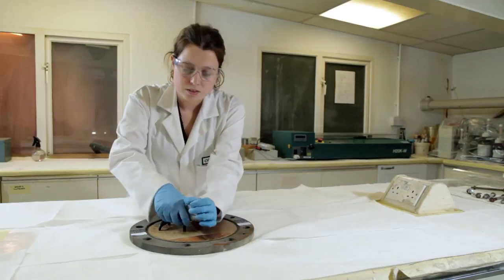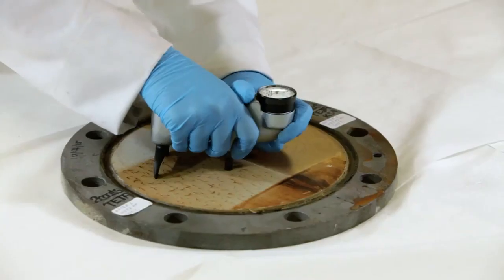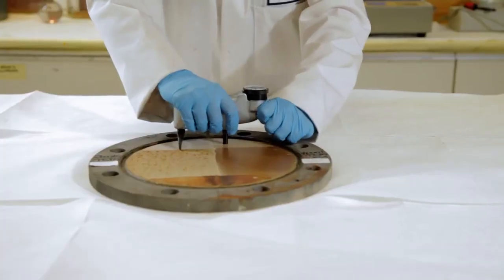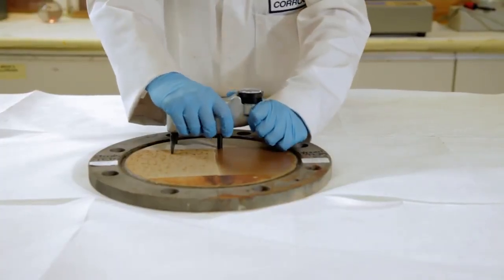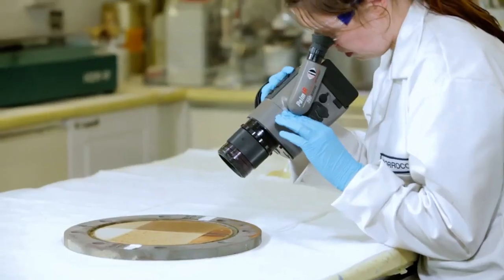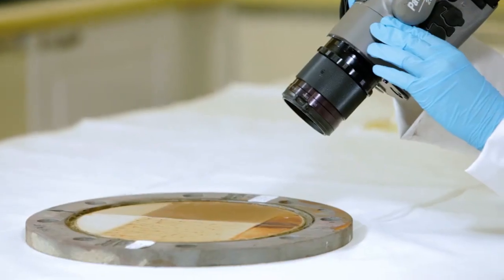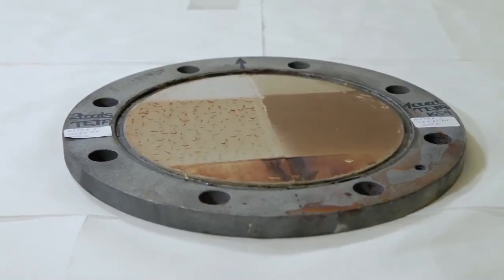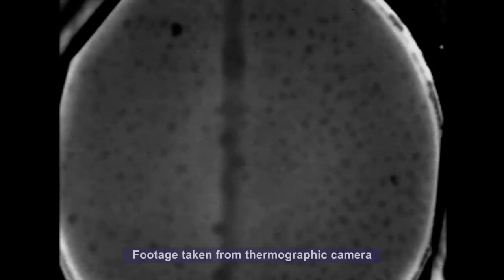At the end of the designated test period, or upon failure of the coating system, the procedures described previously for interim evaluation are carried out, with the addition of the following. The hardness is evaluated in areas of the panel exposed to the liquid solution, vapor phase, liquid-vapor interface line, and outside the test area. A thermographic video camera is used to evaluate if there are any blisters not apparent to the naked eye. Gas-filled blisters show as white spots on temperature decline, whilst liquid-filled blisters show as black spots.